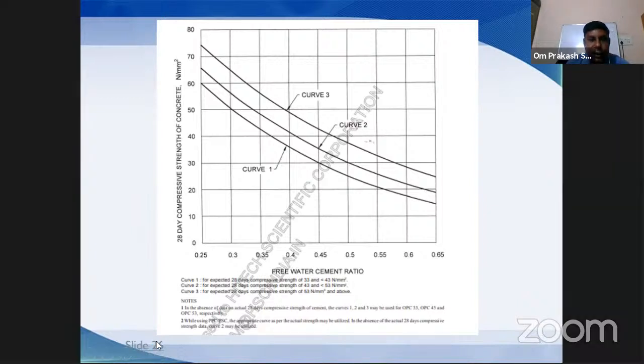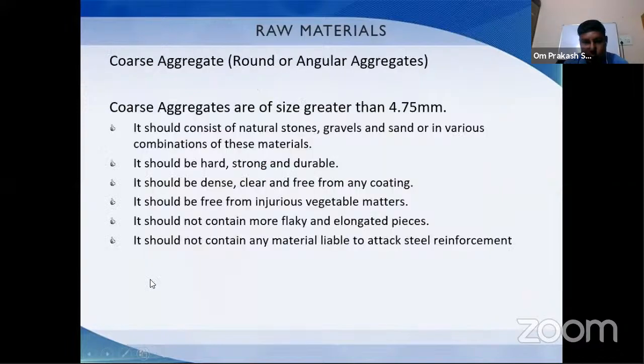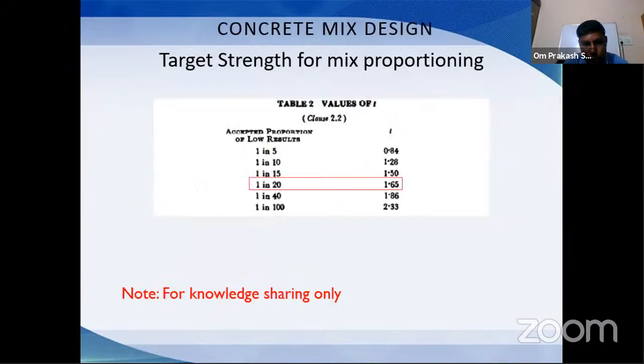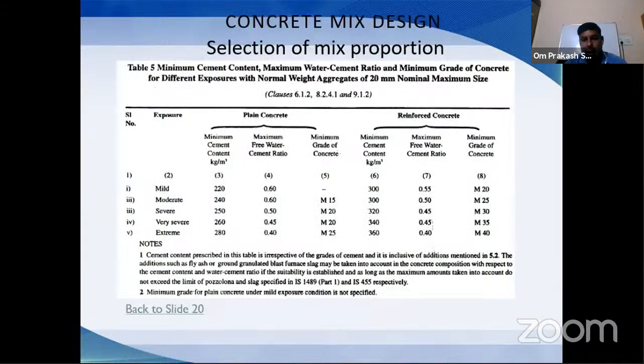But my suggestion is not to go with this graph. Instead, we should go with the table given in IS 456. Here, for M25 grade, the maximum free water cement ratio is given as 0.5. So we can take the water cement ratio as 0.48, 0.47, 0.49, 0.485 according to our requirement. No need to go with the graph. And this water cement ratio is irrespective of the type of cement. It doesn't matter whether you are using OPC or PPC cement, or adding fly ash to the OPC cement. We can choose our water cement ratio from here.